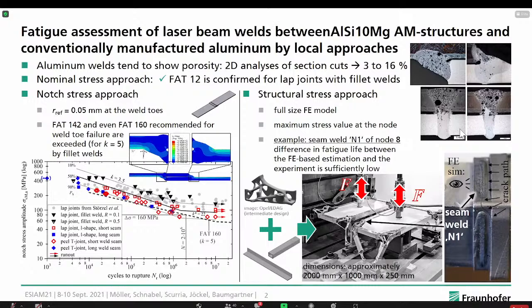Yeah, that's not an easy solution for it, I think. So we've seen this morning that we can introduce some distributions of these pores to the material. In this case, I don't think it's the right way to include all of these pores in terms of a distribution, since we have fatigue failure starting from the weld toes in case of these fillet welds, or from the weld roots. So it's more about investigating how the cracks exactly initiate at these points, instead of trying to include this pore distribution somehow in the notch stress approach, or furthermore the structural stress approach.